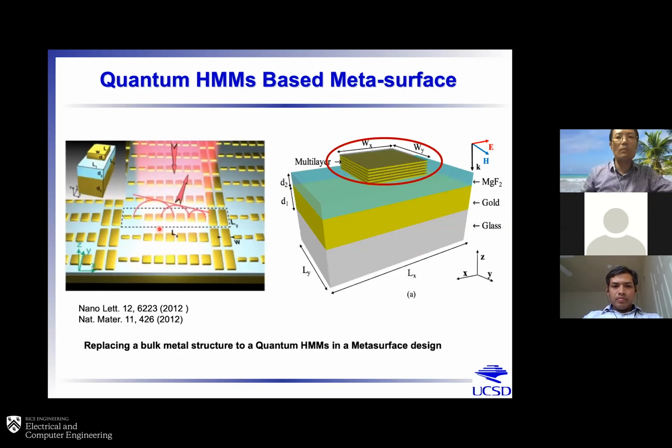And then combine it with metasurfaces. This is one of the reflective metasurfaces. You have an antenna on a mirror. This antenna is a plasmon resonance type of thing, and it will give a different kind of response phase. So what we're going to do is replace the whole thing with this multilayer. You can treat this as a hyperbolic metamaterial. You also have the plasmon resonance, but the additional thing here is that because this metal film is so thin, it also gives you an extremely high nonlinear coefficient. This is just like traditional metal surfaces, with very high intrinsic nonlinearity from these metallic layers.